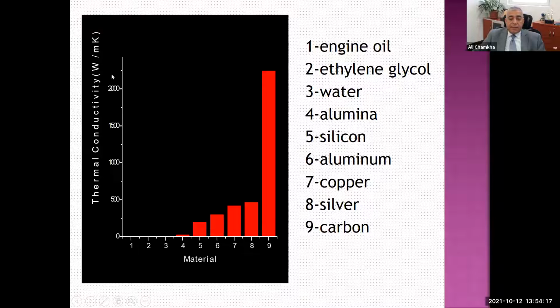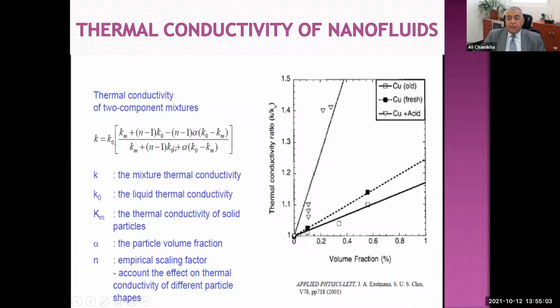Okay, if you look at typical thermal conductivity for some fluids, engine oil, for example, is one. You cannot see it for the scale shown on this graph. Ethylene glycol and water have very low thermal conductivity. They are here. While alumina, you will have this. This is for alumina. Number 8, for example, is silver. Copper is heavily used in industry. Copper is number 7, which is here, much higher than water, of course. So this is why copper oxide is being used a lot. Now, for carbon, you see much, much higher thermal conductivity. These are types of nanoparticles that you can use in fluid. You enhance the thermal conductivity.